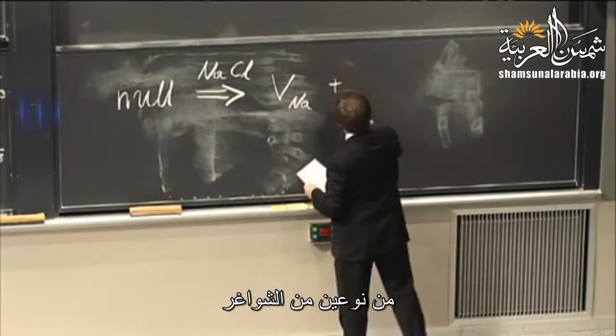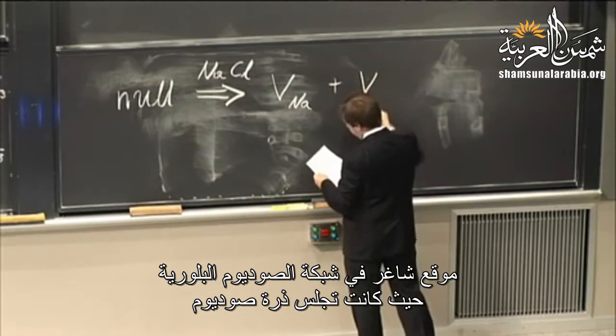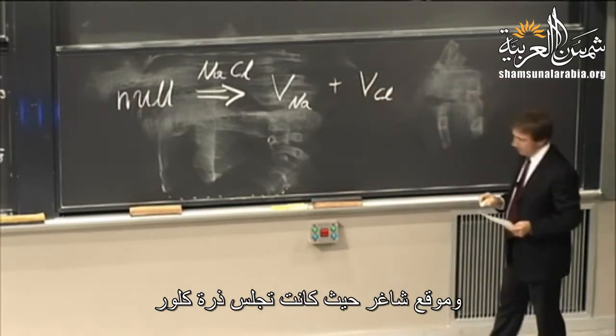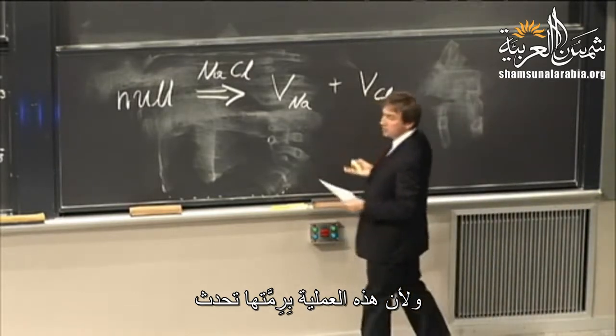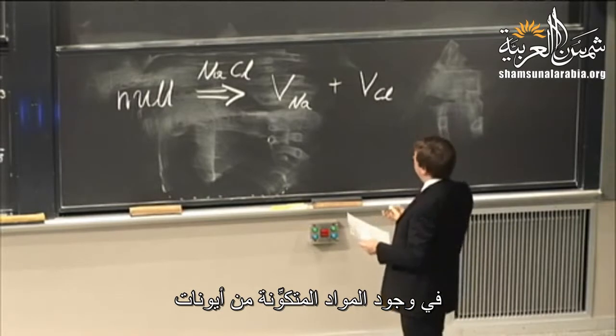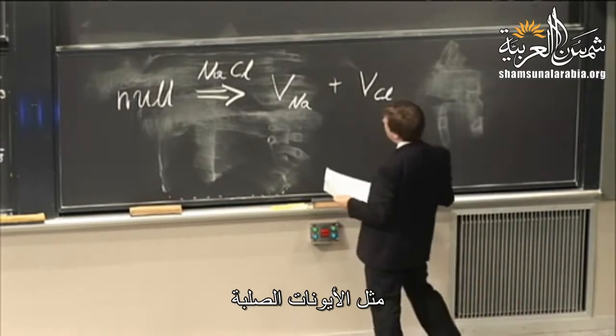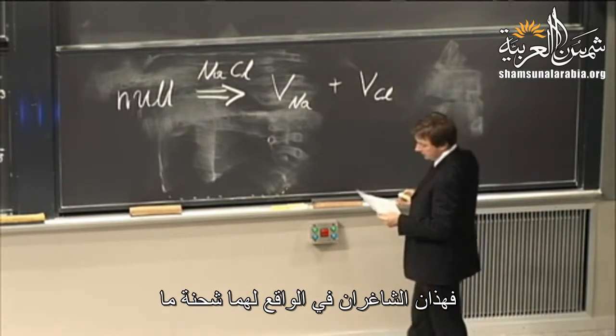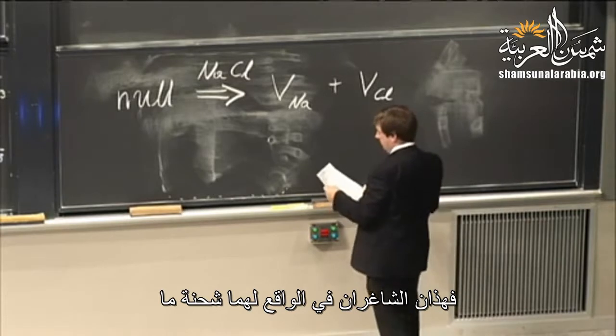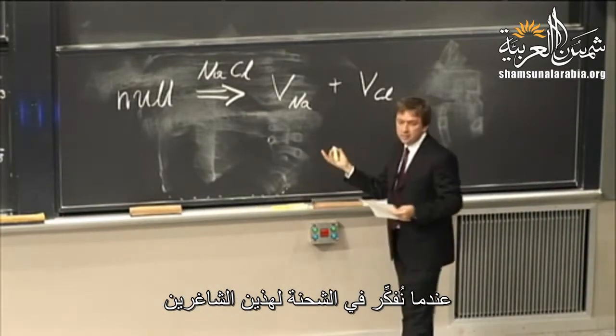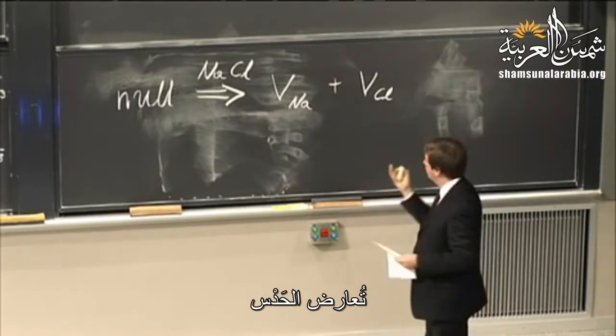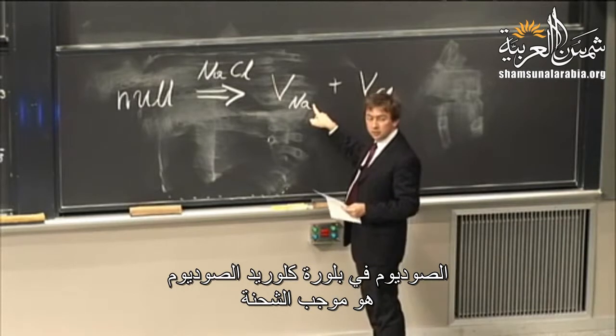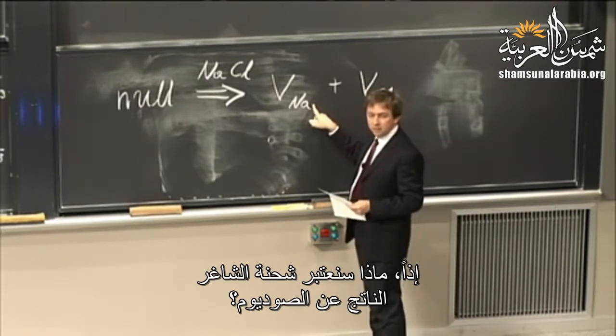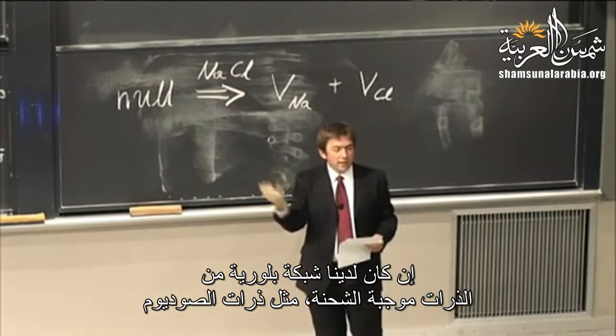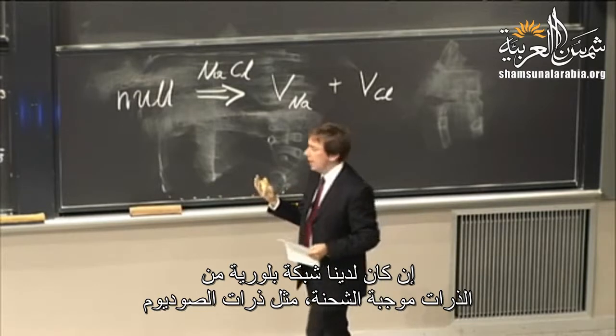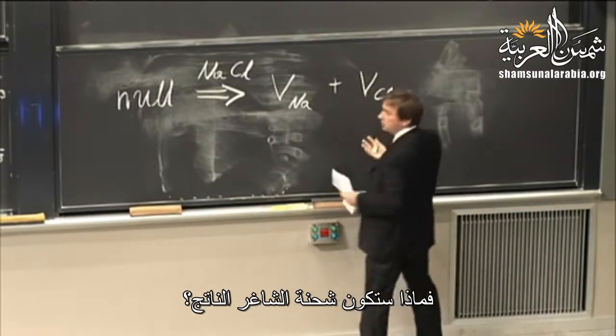A vacant site on a sodium lattice where a sodium atom would have been sitting, and a vacant site where a chlorine would have been sitting. And because this entire process takes place in materials that are composed of ions, so ionic solids, these 2 vacancies, in fact, have some charge on them, right? So when we think about the charge of these vacancies, it's a little bit counterintuitive. The sodium in a sodium chloride crystal is charged positive, right? But what does that make the vacancy? If you have a lattice of atoms that are charged positive, like the sodium atoms, and you remove one of them, what is the effective charge of that vacancy?